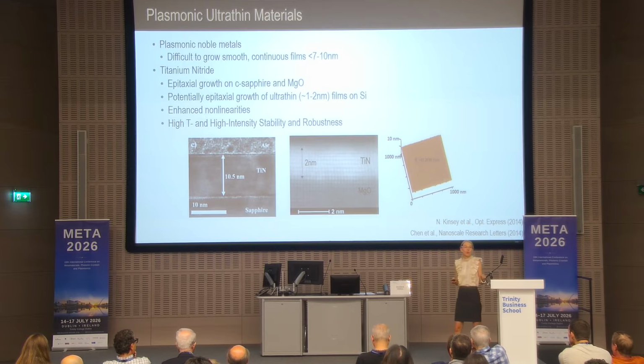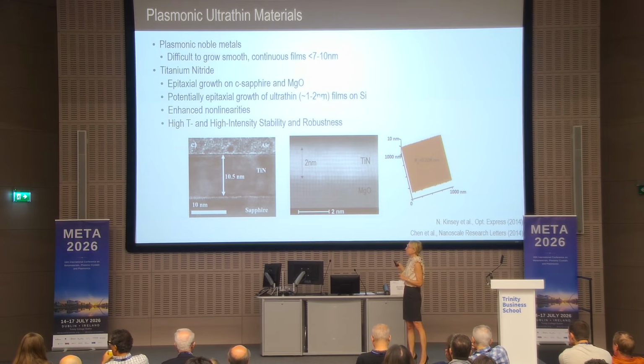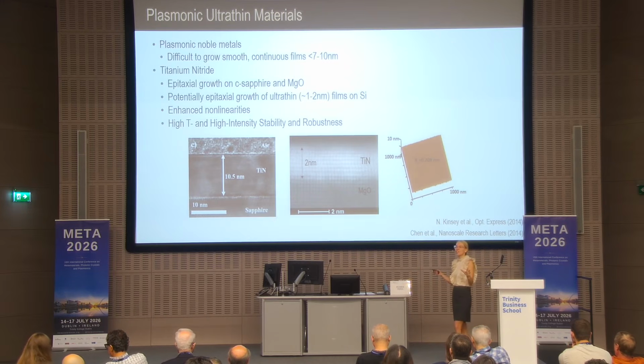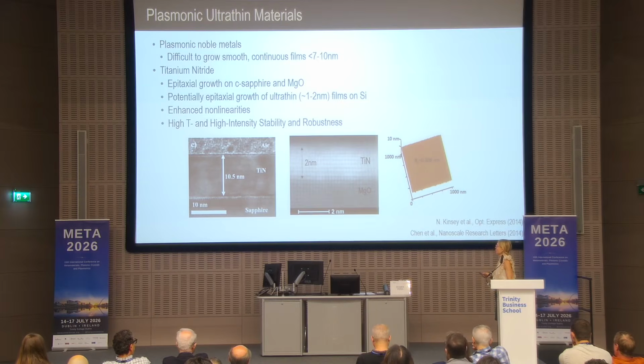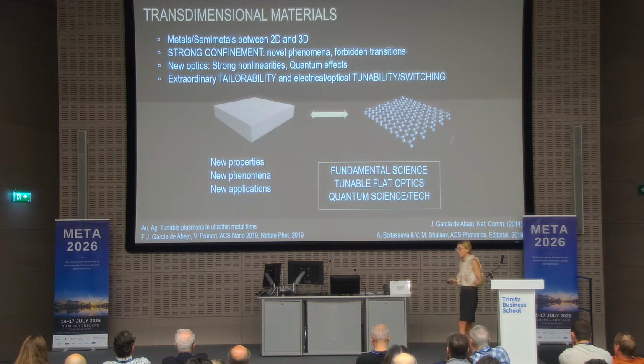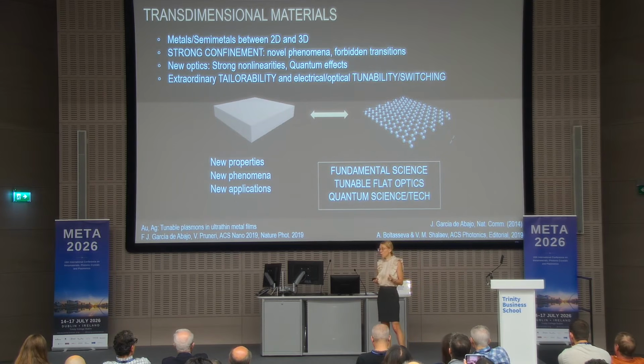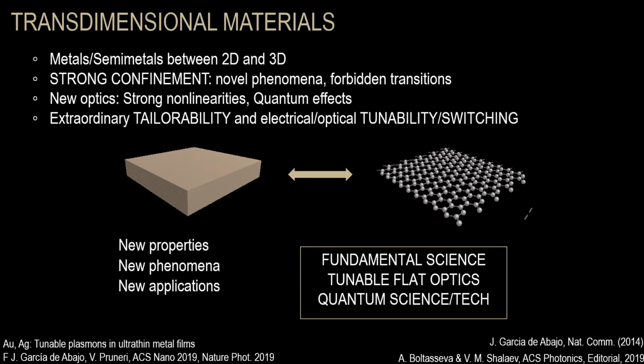So let's look at what happens if you go to ultra-thin titanium nitride films. We were able to go down to 1-2 nanometers. Again, this is only possible because you have this high degree of epitaxiality. You don't have any islands, you just grow on a lattice-matched substrate. Going down to 1 nanometer means you are left with about 5 atomic layers, so it's really a transitional regime between conventional thin films and true two-dimensional films. What we found is that this is a totally different regime of operation. As I said, it resides somewhere in between, but it opens up a lot of opportunities, both for new optics and, as I will show later, for exploration of new physical effects as well.